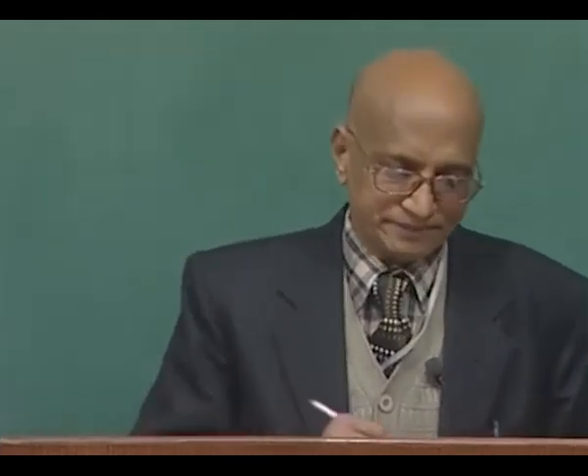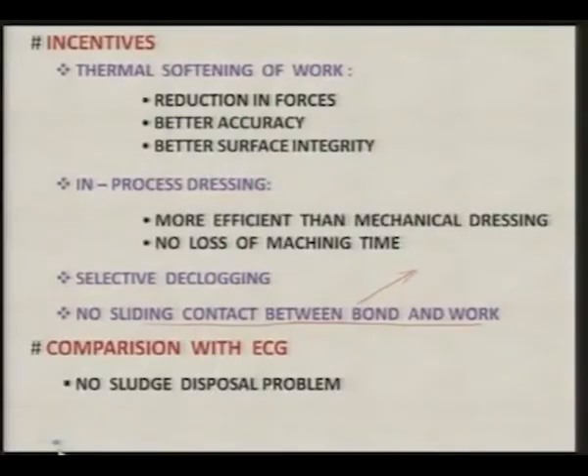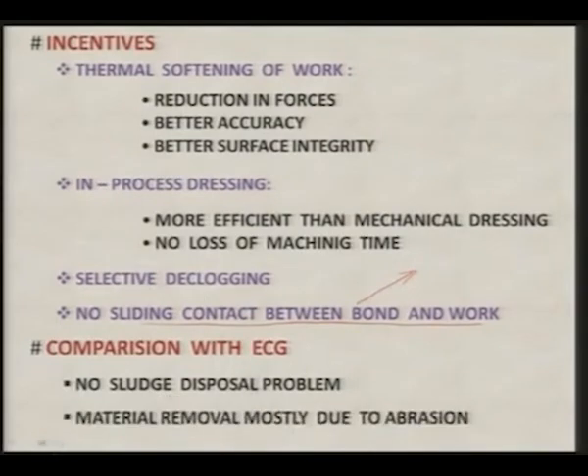They block the inter-electrode gap many times, and short circuit probability is much higher in case of electrochemical grinding compared to electrochemical machining. But in case of electric discharge diamond grinding or electric discharge abrasive grinding, no such sludge formation is there. So, short circuit probability is minimal.